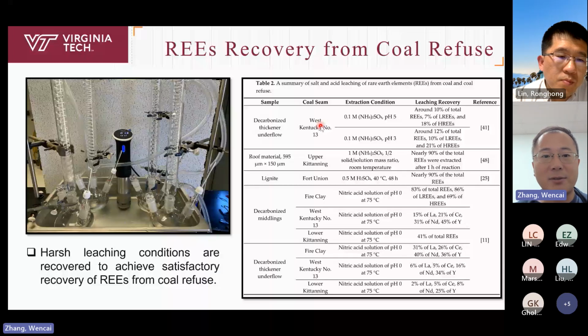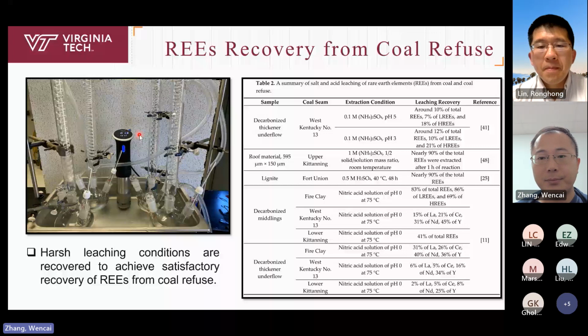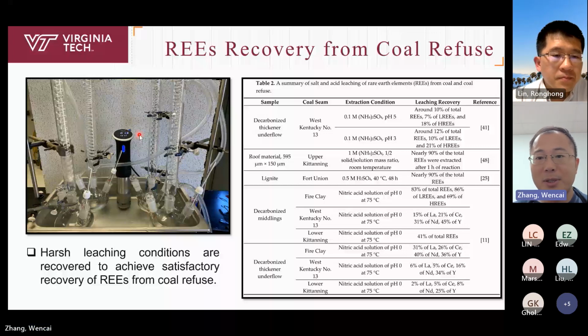We call it leaching. It's very easy to understand. You mix the solid particles with a solution that contains some chemicals such as sulfuric acid. Because the acidity of the solution is high, some minerals will be dissolved. In this way, you can get some recovery of the rare earths from the coal refuse. We did a lot of work, and we found that for most coal refuse, the rare earth minerals are very difficult to dissolve with mineral acids such as sulfuric acid. This table shows some of the results that we obtained. It tells you that recovery from the coal refuse is very difficult to achieve using leaching alone.